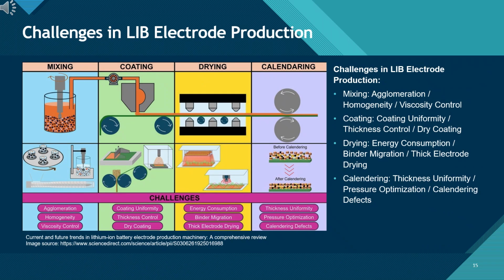Challenges in LIB electrode production. This slide summarizes the major technical challenges in the electrode manufacturing stages of lithium-ion batteries. In mixing, achieving a uniform slurry is essential. Poor dispersion can cause particle agglomeration, non-homogeneous electrode composition, and unstable viscosity, all of which lead to coating defects downstream.